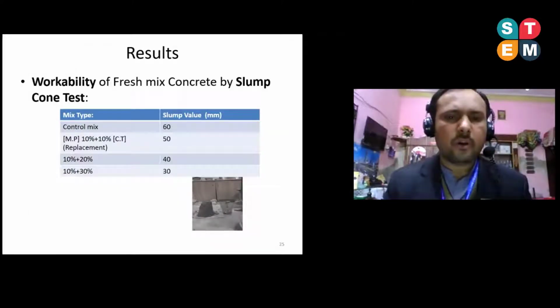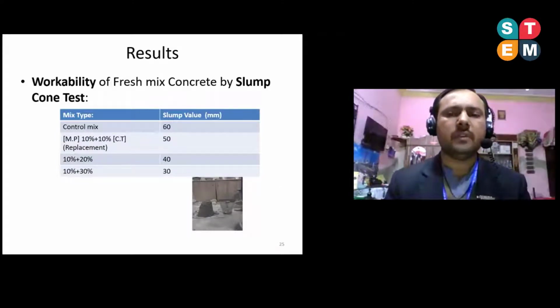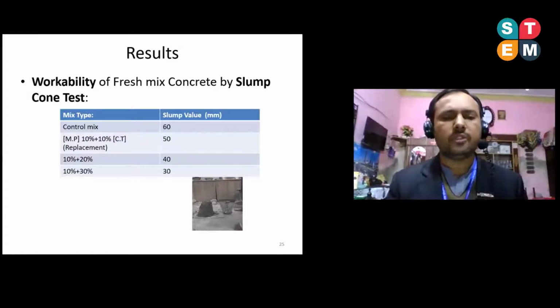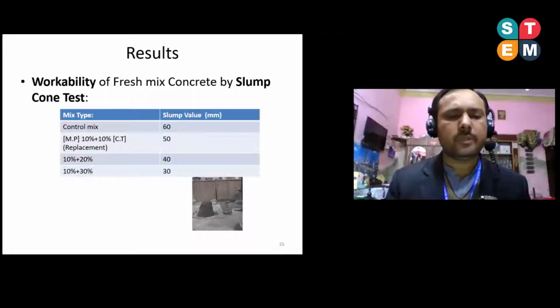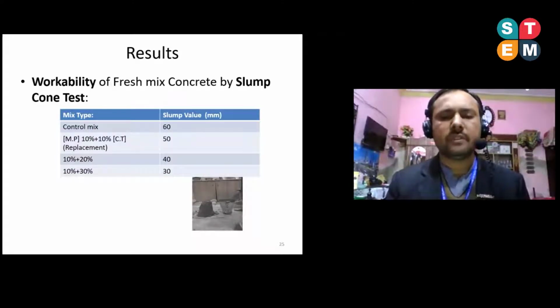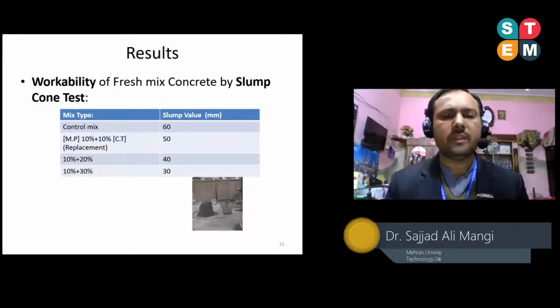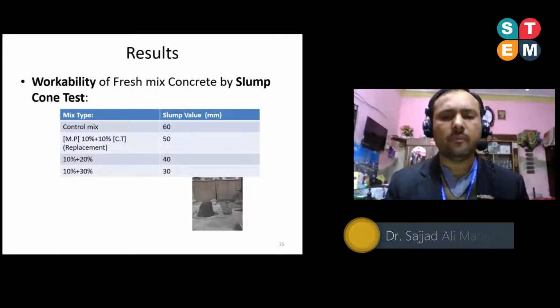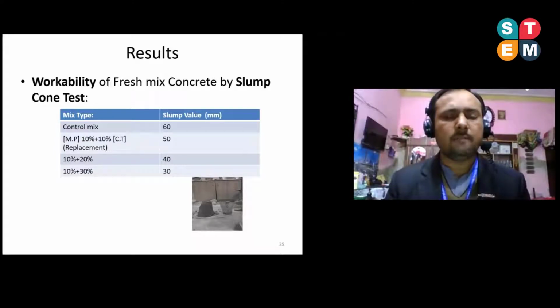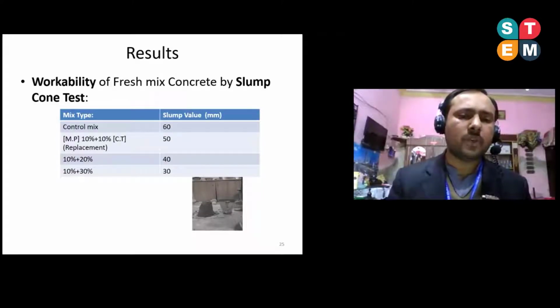And these are results of fresh concrete. These are the results of workability, which were conducted with the help of slump cone method. You can see here the control mix. Control mix means without any waste, which shows the slump value is 60 mm. And C1 means the marble powder 10% and 10% ceramic tile, which shows the 50 mm slump. And when we prepare a concrete with a 10% marble powder and 20% ceramic tile, which gives the 40 mm slump. And when we prepare the 10% marble plus 30% ceramic tile, which gives 30 mm slump value, it shows that when we increase the amount of waste material, which decreases the slump value, because when we use the waste material, it absorbs the more water which is present in the mix. Due to that, the slump value is going to be decreased.